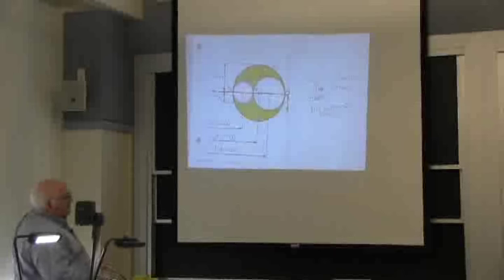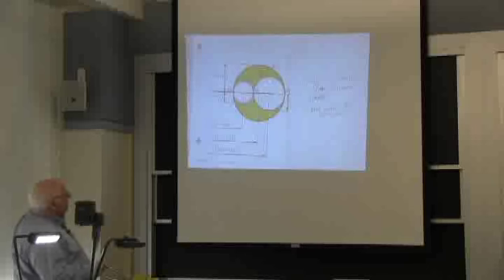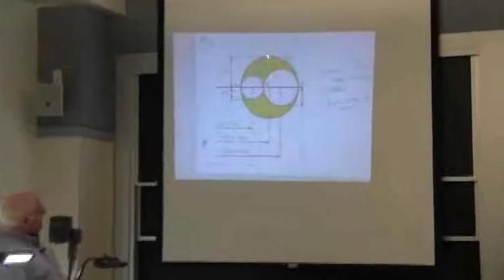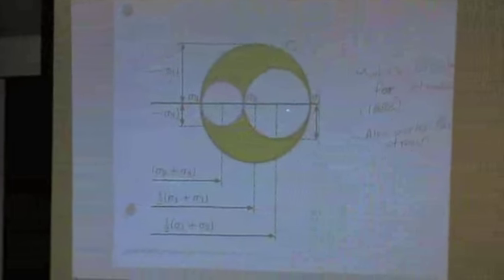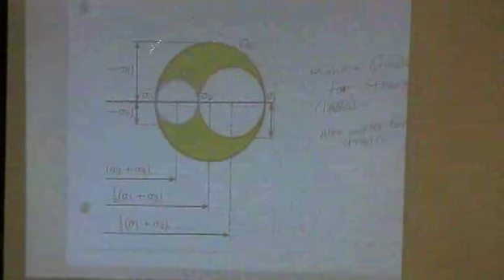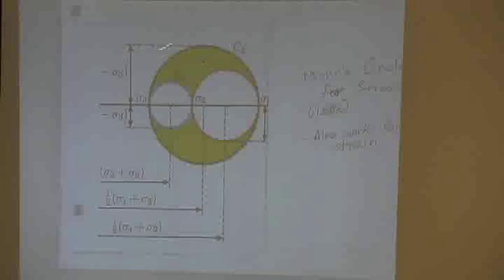You plot them on the horizontal axis, and then you find that there's a construction that says that the sum of sigma 1 and sigma 3, divided by two, which will be the center of the big circle, will give you at any angle, remember this critical resolved shear stress is at some angle that it's actually shearing, you can calculate the angle. The maximum shear stress will be at 45, and this would be 90 degrees. When you draw the circle around the principal stresses, you will get the shear stresses. So the vertical axis becomes the shear stresses. The shear stress is half, which is the radius, half the diameter of the circle. And there's one between each pair of these principal stresses. You have 3 circles for any 2 combinations of these 3.